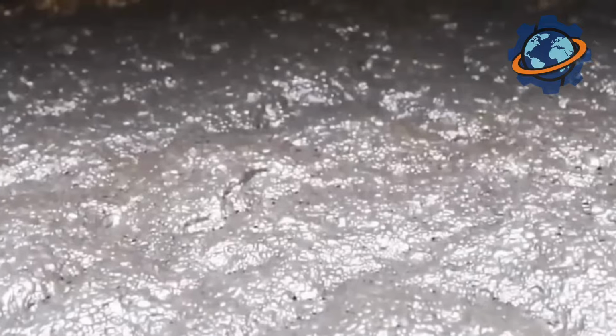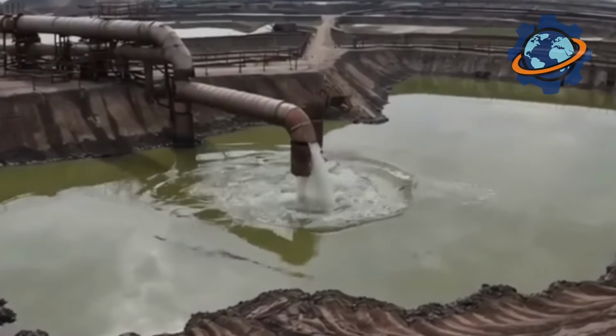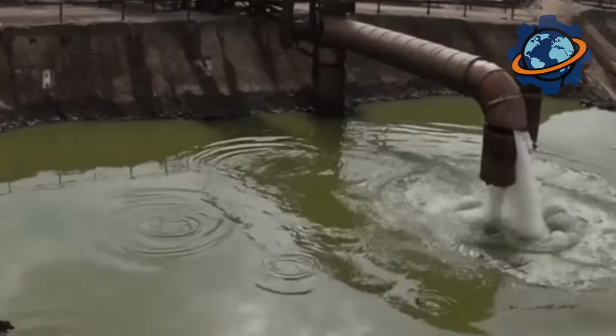One of the most common methods involves mixing the crushed ore with water and special reagents. These reagents selectively attach to the surface of the rare earth minerals, making them water repellent. Air is bubbled through the mixture, creating bubbles to which the hydrophobic minerals adhere and rise to the surface, forming a froth that is then collected. Heavier particles settle faster, allowing them to be separated from the lighter ones.